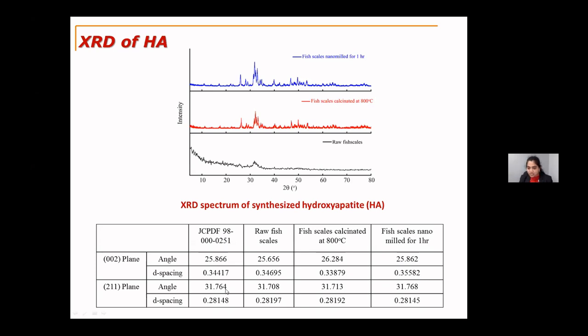Even for the 211 plane, the angle is 31.764 for the standard one and 31.768 for the nanomilled fish scale. And the spacing is 0.28, and the one which we got also has 0.28. So for the synthesized hydroxyapatite particles, based on this, we can say that this can be used for commercial applications or for biomedical applications. So now we got the hydroxyapatite, we characterized it, and we confirmed that it can be used for biomedical or commercial applications. And then we proceeded with the development of the polymer nanofibers by infusing this bio-based hydroxyapatite into the polycaprolactone solution.